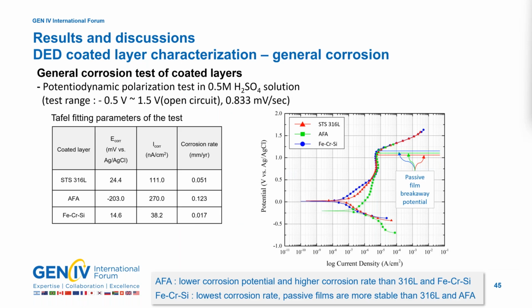For the comparison of the general corrosion behavior of each deposited layer, a potentiodynamic polarization test in 0.5 mole H2SO4 solution was conducted, and Tafel fitting results are listed in this table. Based on the results for corrosion potential, corrosion current density, and corrosion rate, the iron chrome silicon coated layer demonstrated the highest corrosion resistance. Additionally, when considering the passive film breakaway potential, iron chrome silicon was determined to have the most stable passive film.